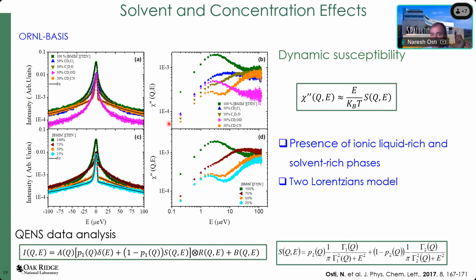When you plot the dynamic susceptibility as a function of the energy transfer, you simply use this expression to translate the dynamic structure factor S(Q,ω) to the dynamic susceptibility. Once you plot it, the number of peaks as a function of the energy transfer corresponds to the number of dynamic processes present in the system, and the position of the peak gives you the time scale of the dynamic processes. If you look at this dynamic susceptibility, you can see two distinct peaks, one at low energy transfer and another at higher energy transfer, indicating that we have two different types of dynamics in the system.